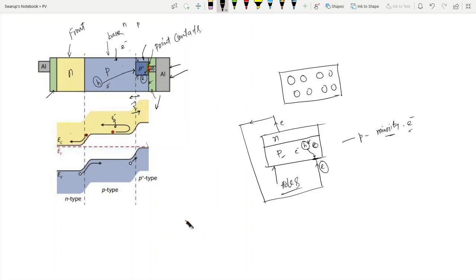This kind of field is called back surface field. This back surface field is produced because of the doping concentration, one is P, one is P plus. So we have back surface field at this interface. We could separate these minority electrons from the electrons coming from the metal contact, which is collected by the emitter layer, I mean, from the emitter layer on the front contact. So this concept is very important. Hope you understood this concept. This is how we make the back contacts for the solar cell.